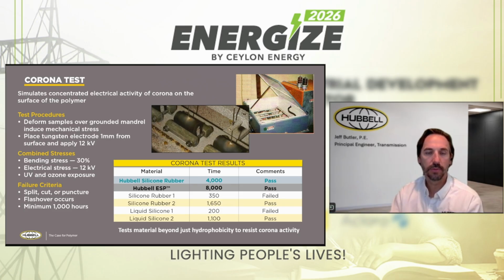In this test, we take a piece of rubber and bend it over a grounded mandrel, just a steel metal piece. As I mentioned, we put an electrode near the surface at 12 kV, and then we energize it for a minimum of 1,000 hours, and you can see the range.